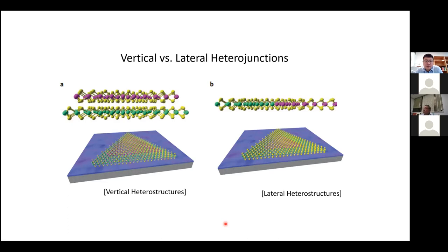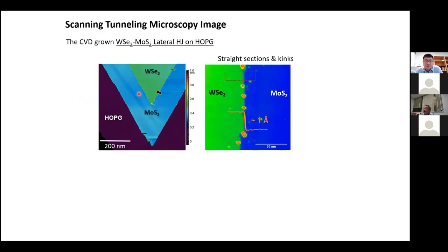So if you think about the lateral heterojunction, in this case, we have WSe2 as a core, MoS2 is the skirt. Then in this paper we show that the WSe2 and MoS2 appear to be chemically abrupt, because WSe2 is higher, MoS2 is smaller in thickness. And electronic structure wise, if you look at the valence band structure, you're going to see the WSe2 show up much brighter, by about one angstrom higher.